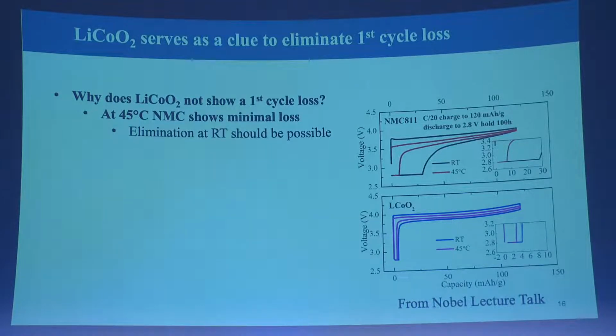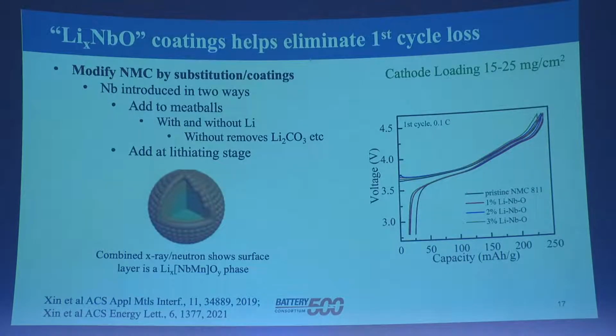In this case, we just charged it up to a fixed capacity, then discharged it at 2 temperatures. And you can see, I think here, the red one is higher temperature, and you can see it almost all goes back in. So this is 45. So we don't have an issue here. Cobalt oxide, you don't have to go to higher temperatures, no first cycle loss period. So we're saying we should be able to take our layered oxide, modify it by, say, substitution or something, to make it look more like lithium cobalt oxide. And that's what we've been trying to do for the last few years.